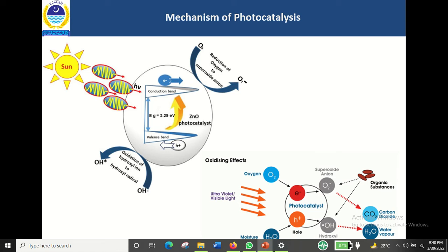However, this band gap suggests that this photocatalyst can only work well under the UV region of the sunlight, but the UV part of the sunlight constitutes only 5%, and 40 to 45% of the sunlight falls in the visible region. So this photocatalyst does not work well under the visible region of the sunlight. It means a large portion of the sun spectrum is not usable if we consider this photocatalyst for photocatalytic activity.